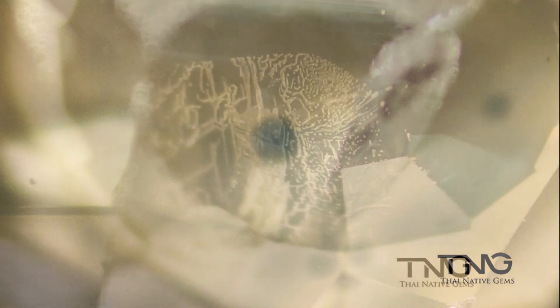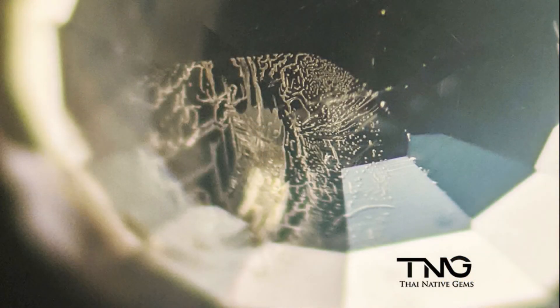Whenever you see a yellow sapphire with these blue halos, it is almost a hundred percent guaranteed the stone has been treated by diffusion — either beryllium or titanium diffusion. These visible signs exist because of the extremely high temperature treatment these stones go through. Looking at the melted crystals image and comparing with the unheated yellow sapphire, you'll notice the crystals are not as defined — they appear more cloudy and unclear. With the experience gemologists have, you can tell these crystals have been subject to heat treatment and are not intact like those in the unheated yellow sapphire.